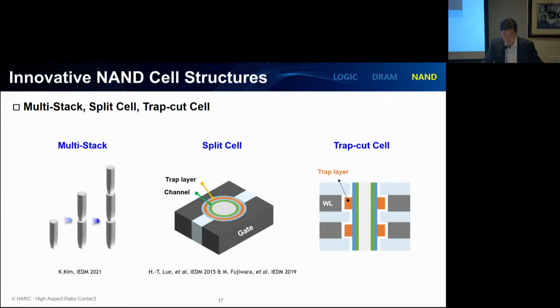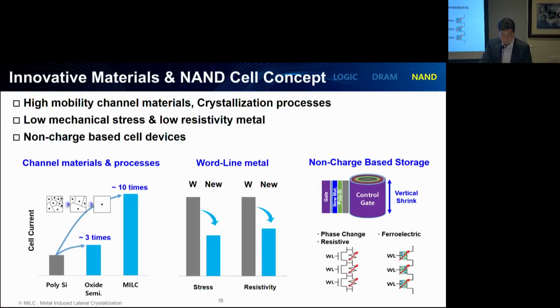However, these structural innovations can mitigate the challenges of the stack height increase, but they cannot stop the total stack height from increasing as more layers are stacked with the ongoing evolution of generations, therefore aggravating the cell current and mechanical instability. So we can mitigate these pressing challenges from the perspective of novel processes and materials.